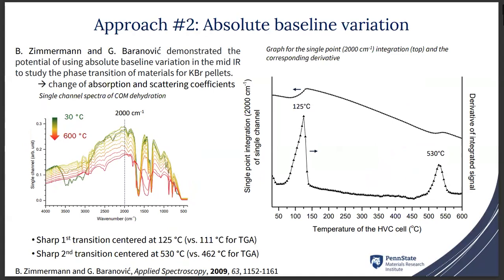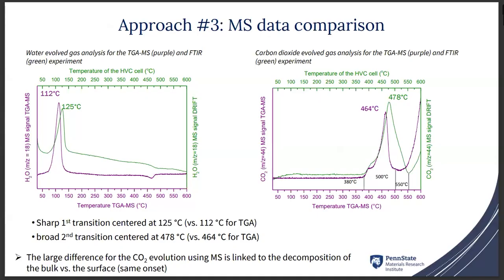And so we have 530 degrees Celsius, where there is still some decomposition of carbon dioxide, but it's very much at the end and not at the optimum of the derivative peak.